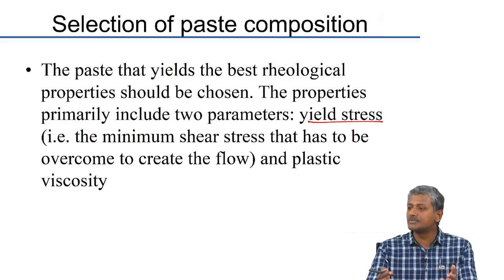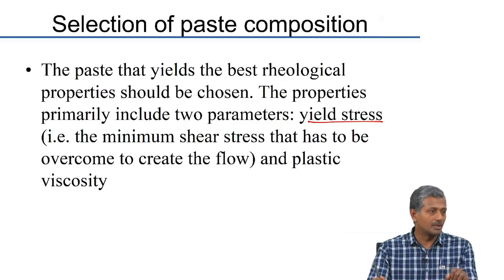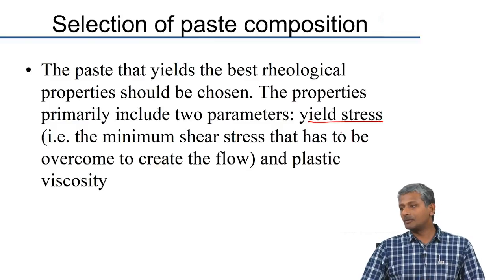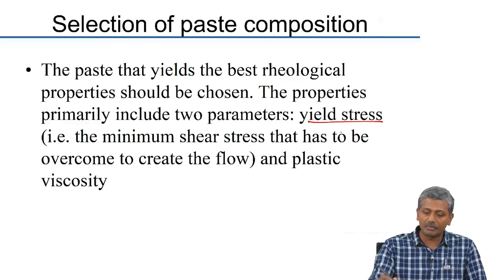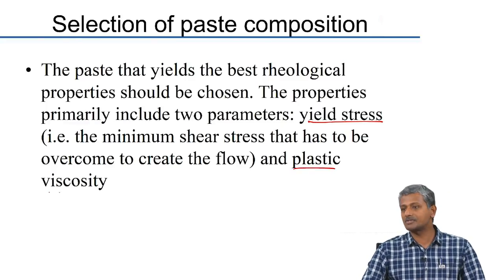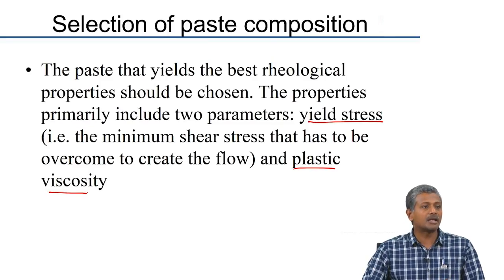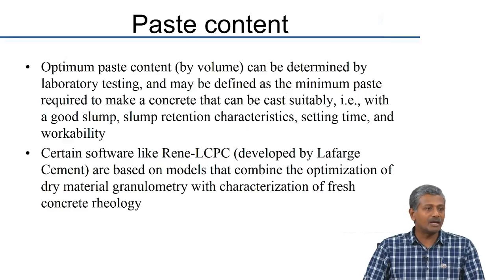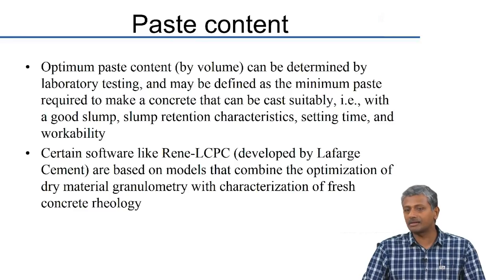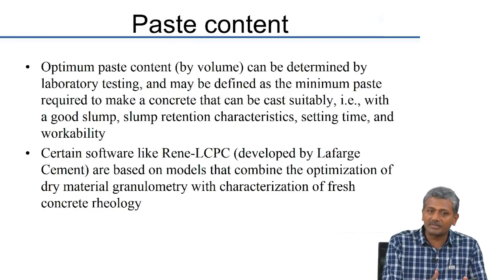Yield stress is the innate quality of the material which prevents it from flowing, and once the material flows, the resistance to flow is governed by the viscosity or plastic viscosity of the material. We will learn later about the different types of rheological models and how we can estimate these characteristics for cement paste and concrete. To determine how much paste is required, we must understand how much void space is left behind when we are packing the aggregates in a given fashion.